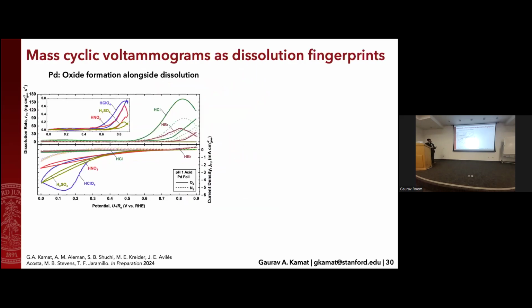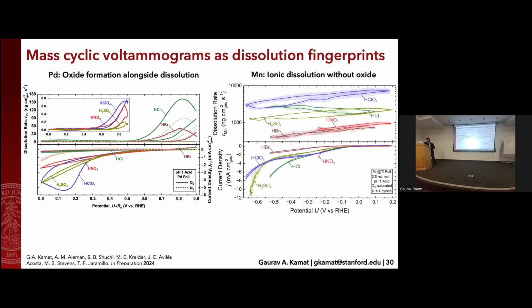And the last thing I'll mention is that these mass cyclic voltammograms are sort of like dissolution fingerprints. They tell us a little bit about the mechanism of dissolution. So I mentioned that palladium and a few of the other metals have this sort of oxide-mediated dissolution pattern. But if we look at manganese, manganese has much more linear-looking shapes. And given that this is just a log axis, it means as you increase your potential, your degradation or dissolution rate is going up exponentially.